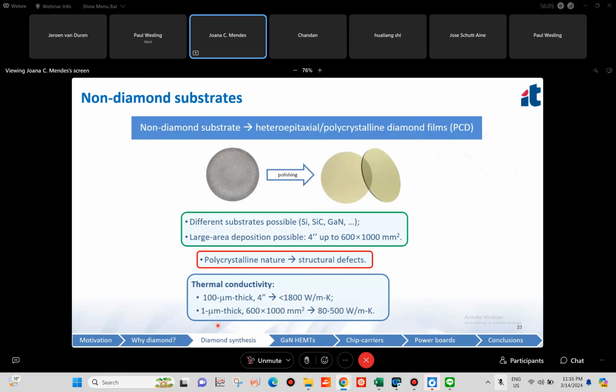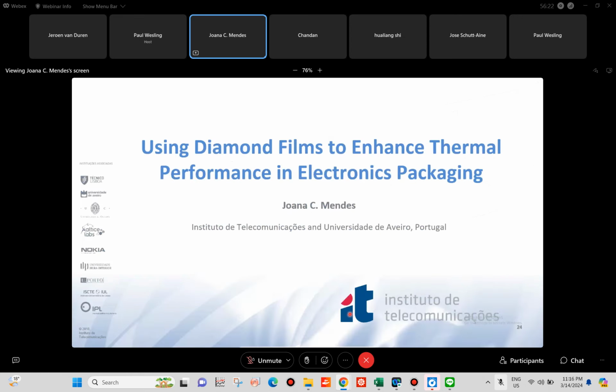And if we go to the very thin films deposited by the linear antenna system, typical values for a 1 micron thick film are in the range of 80 to 500 watt per meter Kelvin, but these values can be further optimized with optimizing deposition conditions. And now that we know everything there is to know about diamond, how can we make diamond? Let's see how we can use it really to enhance the thermal performance in packages.